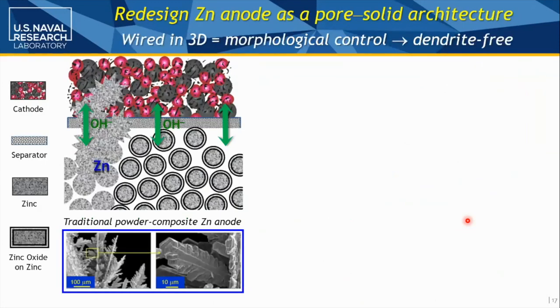So here's our old picture of an active material. I'm not going to specify what it is, ground up with carbon powder, some kind of separator. Zinc is a powder. And as you discharge that in an aqueous electrolyte, the end product is zinc oxide. There are some steps in between that complicate our lives. And so that zinc oxide is not highly conductive, so you start to passivate the metallic, highly conductive zinc. And the part that isn't terribly passivated gets a lot of the local current density, and that's why dendrites form. And they can be seen by eye and probably by satellite.